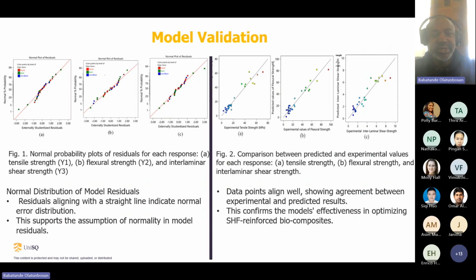Now, to validate the model further, I look at the plot of residuals. Figure 1 is the plot of the residuals for tensile, flexural, and interlaminar, and you can see the normal distribution. All the distributions align directly on the line. They are very close, and this supports the assumption of normality in the model. Figure 2 is the comparison between the predicted and experimental values. You could see the data points align well, showing agreement between the experiment and the predicted results. This confirms the effectiveness of this model in optimizing sun hemp reinforced bio-composites.